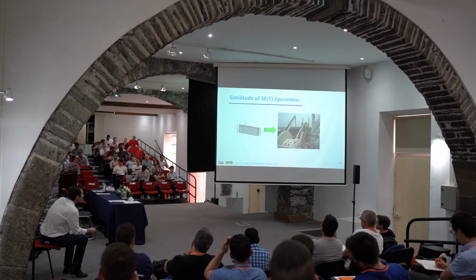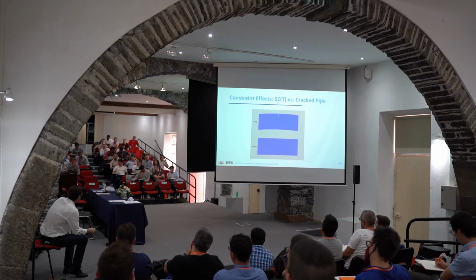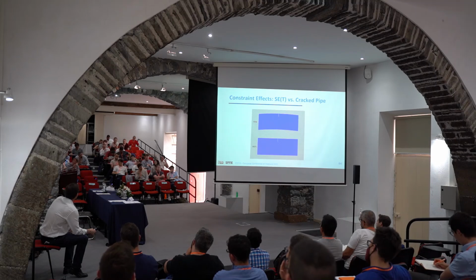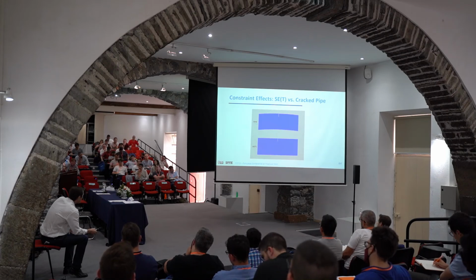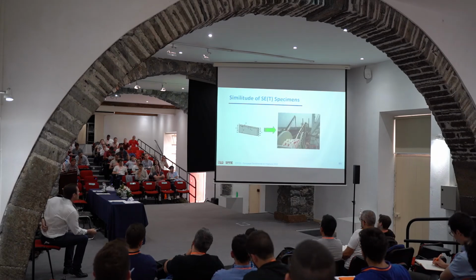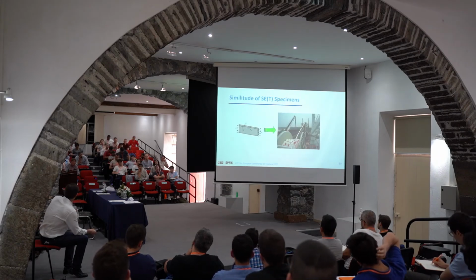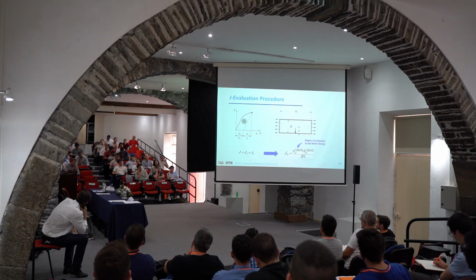Again, my question was whether the similarity of conservative of the SET is valid for both plane strain and plane stress. Yeah, this is plane strain, but plane stress will be the same. Probably the stresses will be a little different because it's plane stress, but the similarity is the same. And as I said, this is similitude, the similarity between the SET and the specimens.